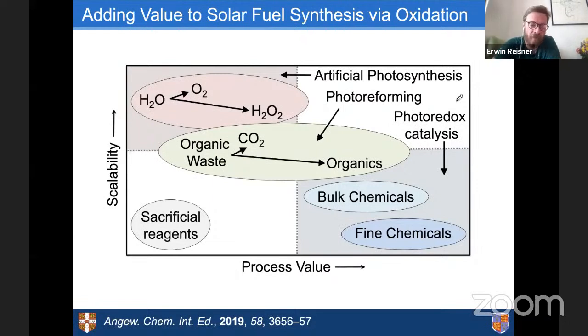So plotting this differently, to justify this approach of bringing value into the process, this is a very simple plot where we have scalability on the y-axis versus process value on the x-axis. If we just start with water oxidation to oxygen, you can see the scalability is clearly a huge advantage, but we're not adding much to the overall process value. On the other extreme, of course, you can think about using organic oxidations to produce fine chemicals and bulk chemicals. This would increase the process value quite dramatically, but then the scalability on a relevant global scale to make a fuel is not there. So there would be this huge mismatch of the one pharmaceutical you want to make versus the hydrogen requirements to support a steel factory, for example.